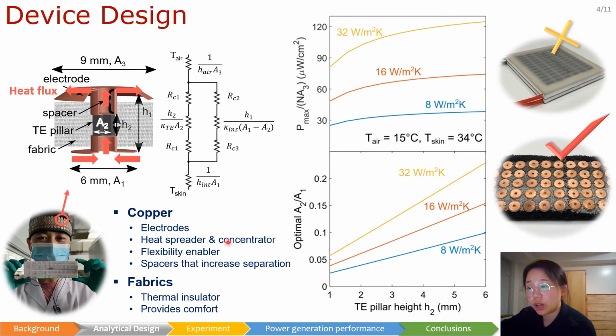The key innovations are that the copper electrodes are not only used for electrical connection, but also as heat concentrators and spreaders, and flexibility enabler. The spacer design increased the separation between the hot side and the cold side, contributing to a larger temperature difference that can generate power. The fabric helps reduce heat leakage and provides comfort for wearing.